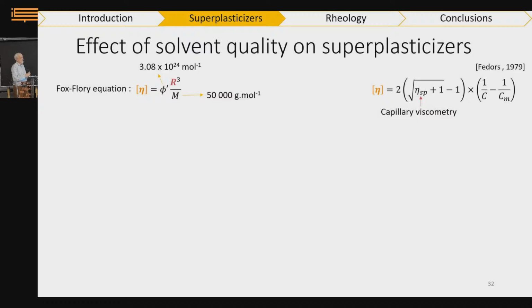That is, we can get the intrinsic viscosity of the polymer in solution with water. So this is an experimental measurement. Based on theory, but this is something that's measured experimentally, the intrinsic viscosity. And then again, we go back to our forefathers, Flory, and there is a model linking the intrinsic viscosity to the size of the polymer.